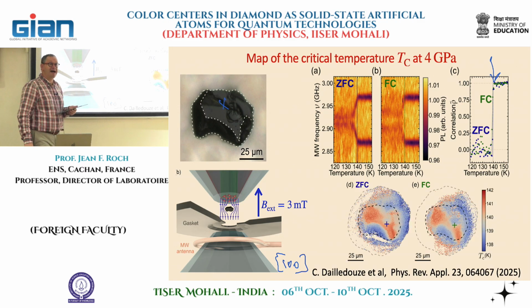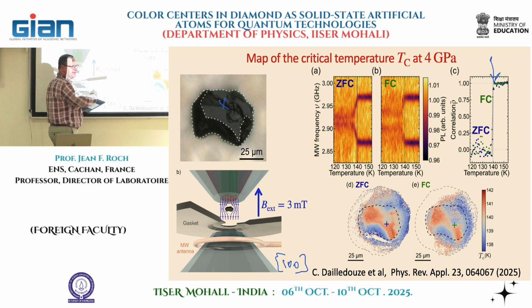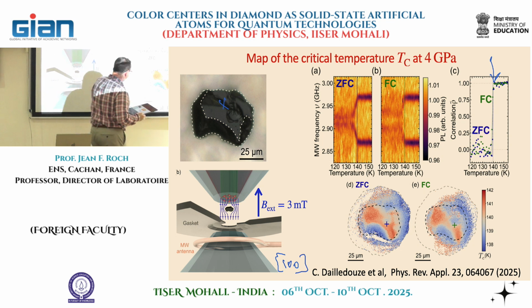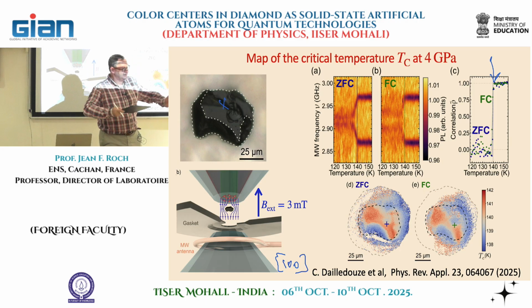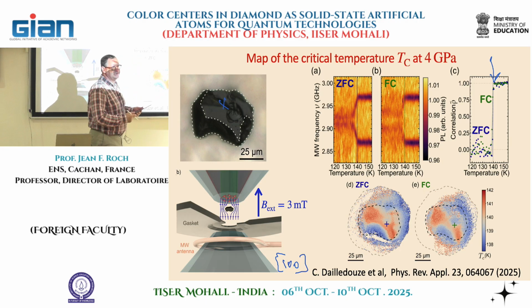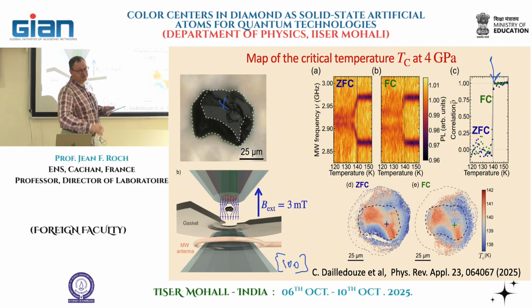And we can make a map of the magnetic field of the Tc, because we're using our data, we have this information all over the sample. So we can do the Tc map, and we can have the value of the Tc. Of course, there are values obtained outside due to the Meissner effect that creates a distortion of the magnetic field distribution even outside the sample, but this is not relevant data, of course.